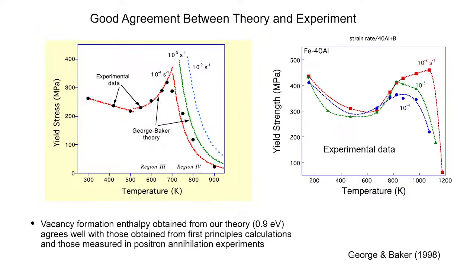And of course, this is not strain rate sensitive, but this is strain rate sensitive. So the faster the strain rate, the more the curve shifts to the right. So you can easily see that and imagine that. And so which means that if you now draw a curve at different strain rates, you will see that the peak temperature will shift to the right, and that's in fact what we see. The peak temperature shifts to higher values and to the right as you increase the strain rate.